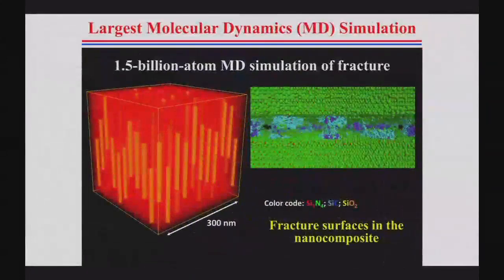And this is the largest simulation we have done, as I indicated to you before. This is for a composite. On the left-hand side, the red part is a silicon nitride matrix. Silicon nitride is a ceramic. It's a very hard ceramic, but it's brittle. In order to make it less brittle, but the strength should stay the same, we embed silicon carbide fibers. This is actually done experimentally also. And then we studied fracture in this composite, and it turns out it's a very tough ceramic.